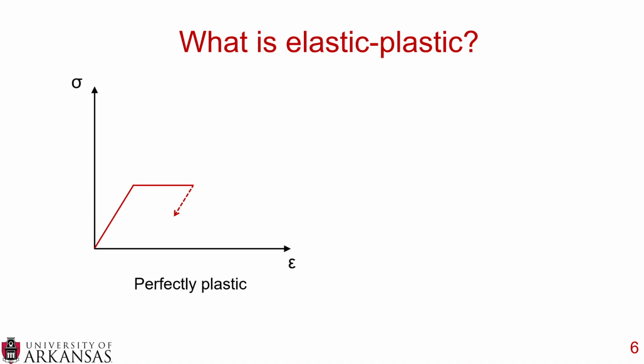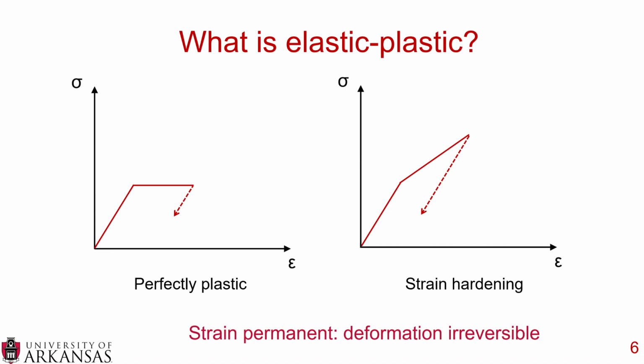Now, when we incorporate plasticity into this, this means we apply some sort of strain, but then it does not return to zero. So you have a perfectly plastic material where it returns back to a stress of zero along the same slope as the loading that was applied, or you have something called strain hardening, where there's some sort of kink in that loading cycle, but then again, you return back at the same slope, but there is some sort of permanent strain. And so here with an elastic plastic material, you introduce some deformation, and that deformation is irreversible.